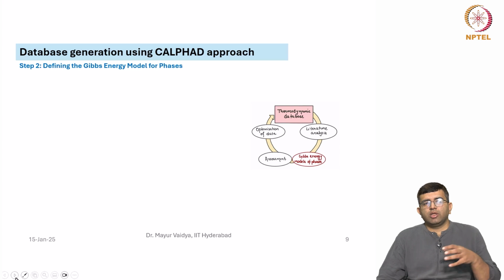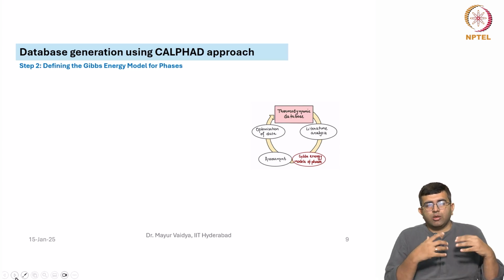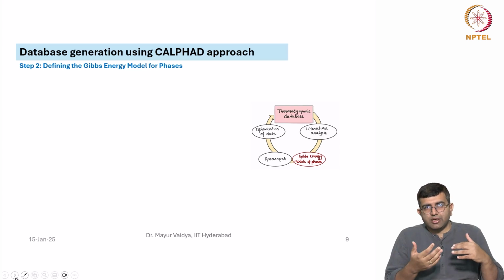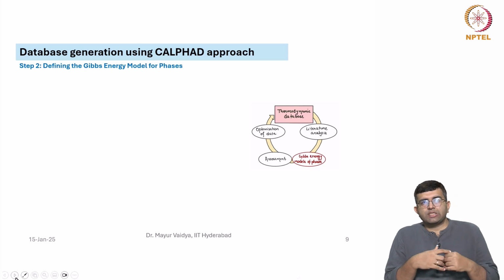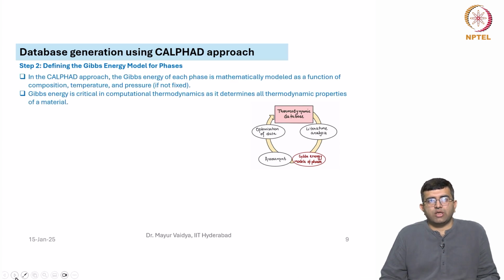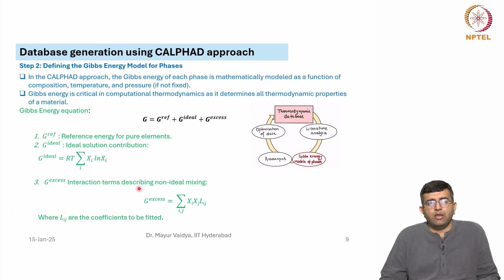Then once you have gotten the data by either experiments or by theoretical approach or by existing databases and so on, the second step is to define the Gibbs free energy model for those phases. So, in CALPHAD, the Gibbs energy of each phase is mathematically modeled as a function of composition, temperature and pressure. If pressure is fixed, then it is a different thing. Gibbs energy is critical in computational thermodynamics, as it determines all the thermodynamic properties of the material. This we have already seen.